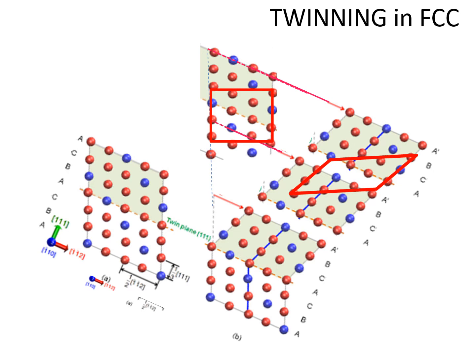Here's another illustration. We're looking at the 110 direction. The twin shear direction is 112. The twin plane, the perpendicular, is 111. I'll be talking more about this and illustrating it in the videos where I can do that with the ball models.